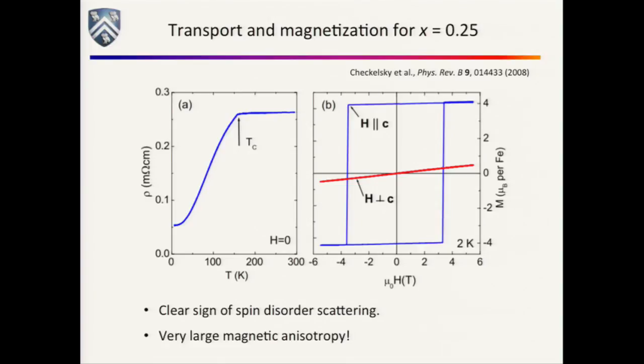The anisotropy of these things is quite remarkable. Here's magnetization on a big crystal, this is iron a quarter, and what you see is this incredibly square hysteresis loop. From the standpoint of actual magnetic anisotropy, these materials are very similar to what you would see in the rare earth magnets. They're really anisotropic. They're very similar to what you'd see in something like samarium cobalt or neodymium iron boron. Of course, they're not that technically useful because the TC is so low, but interesting to think about.